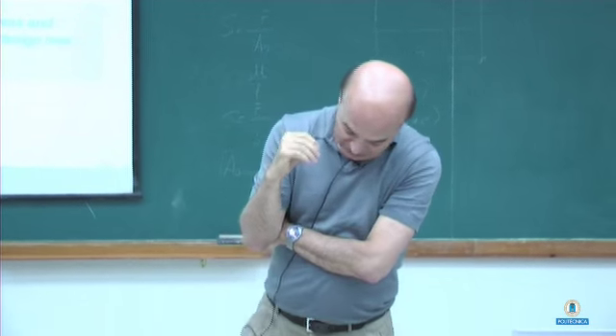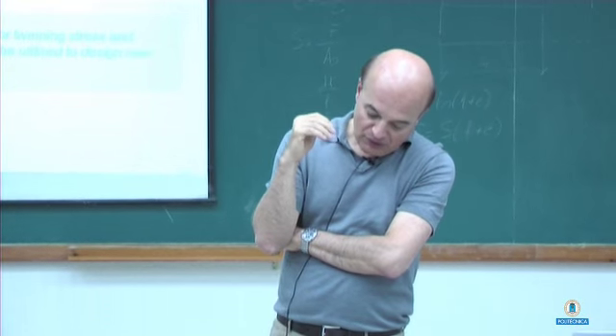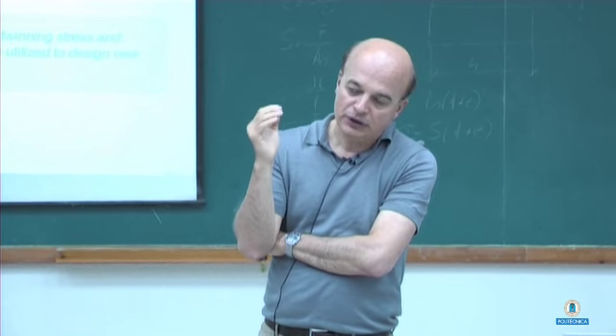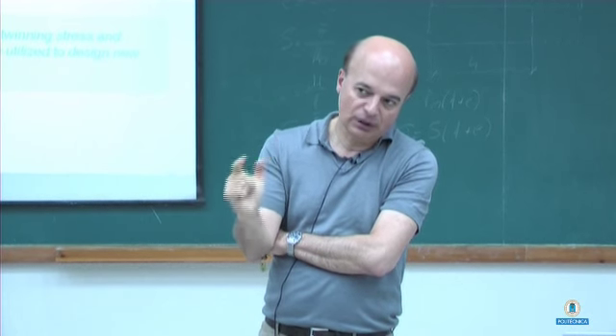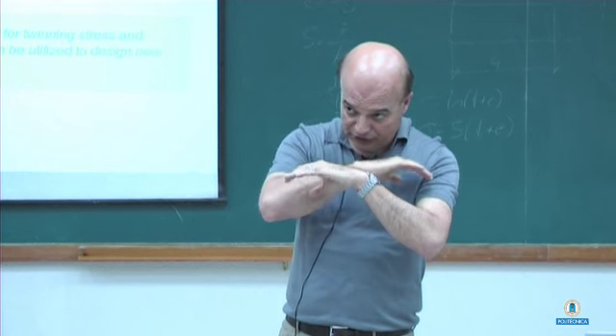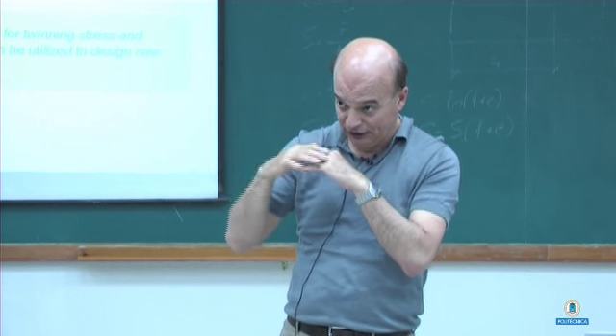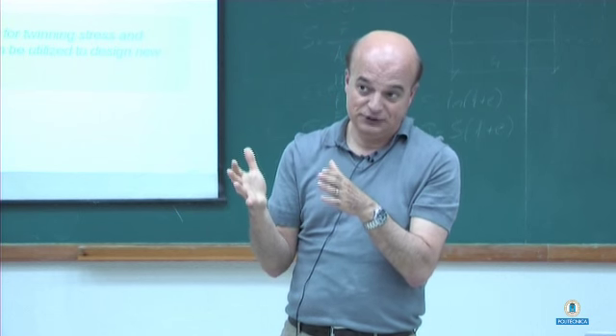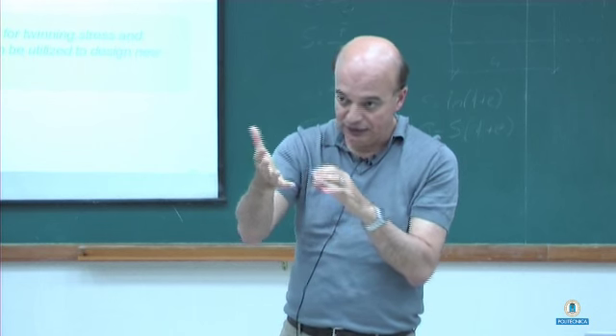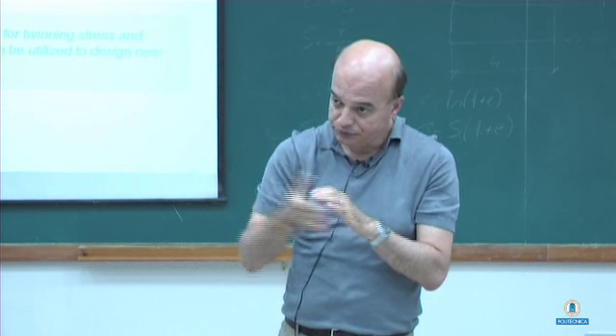So in the twin migration, if you're looking at migration over long distances, for example, you'll hit other barriers. In the model I present, I don't have any external barriers to twin. In other words, I move the atoms, I create the twin, and I propagate the twin unhindered. That is migration, but no obstacles. So if you have obstacles like slip band, or another twin, a crossing twin, you have to do a different modifier analysis.